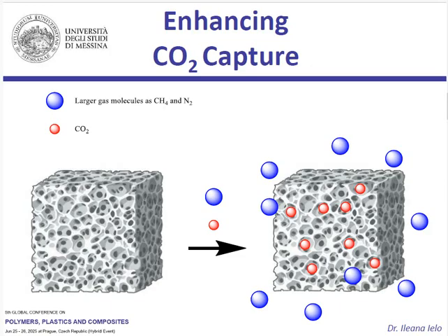Biopolymeric membranes can be designed with precise molecular porosity. This tailored porosity is what enables them to selectively separate CO2 from other gas mixtures, such as nitrogen and methane, which is critical in flue gas streams. Furthermore, we can significantly enhance both carbon dioxide permeability and selectivity by incorporating functionalized and cross-linked microporous particles into these membranes. This process allows us to create extremely small pores, ranging from nano to ultra-nanopores, further optimizing capture efficiency.